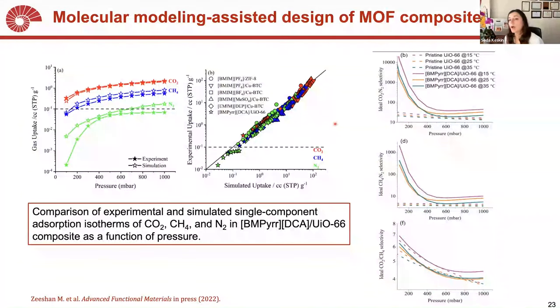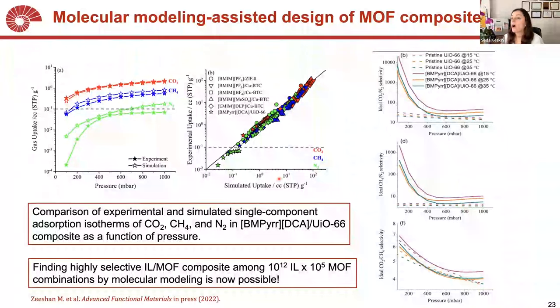Using this approach, we were able to improve the selectivity of UiO-66 from 30s up to 100 at regular pressures. And at low pressure region, we were even able to see very, very high selectivities because obviously nitrogen was not able to enter into the pores of the composite. So because of the ionic liquid, we were able to find a really highly selective, almost completely CO2 selective over nitrogen composite using this computational approach.